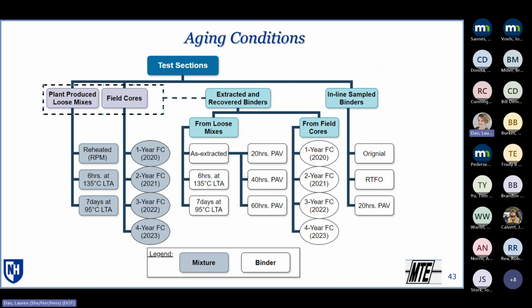And then based on some of the initial results, we wanted something that was a little bit further down the line in terms of the aging, and so added 7 days at 95 degrees C. So for all those mixture tests, we've got 3 different aging conditions. We've got field cores that we tested. So those were collected every year. And then for the binders, for all of those, binders were extracted and recovered from the original loose mix.